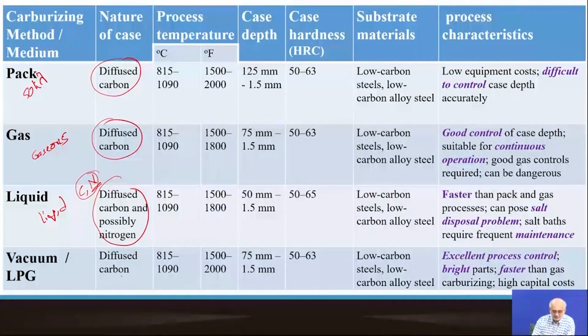Temperature shows slight variation as we go to, for example, gas carburizing. There could be somewhat slightly higher temperature used, but the depth that we are talking about will be higher in case of pack carburizing or solid carburizing, because you have very little control over it. Once you charge and heat, carbon diffusion you cannot stop by pressing of a button. You have to take that box out and then cool in air and then break it open and then remove the charge. During all the process, there is some residual temperature, and as temperature is higher than room temperature, the diffusion of carbon continues. The temperature decreases, but not to room temperature instantly. So diffusion continues, and as a result, you have slightly higher case depth in case of pack carburizing.